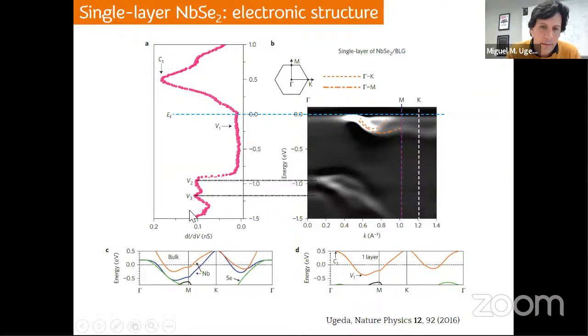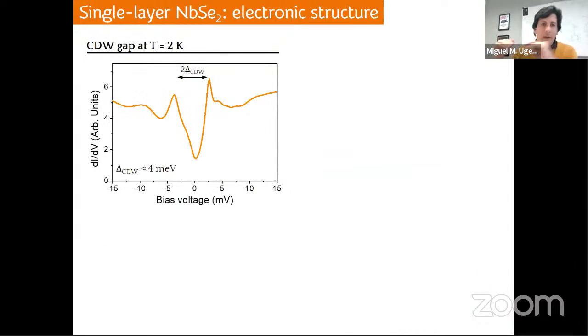And here I show you a dI/dV spectrum taken on this single layer, where you can see the density of states looks like this, and that's it. If you go now close to the Fermi level and at low enough temperatures, for example, I show you a dI/dV curve taken at 2 Kelvin, above the critical temperature for the superconductivity but well below the critical temperature for the charge density wave, what we usually see is a gap with a finite conductivity that we identify as the charge density wave gap, which has a width of 4 milli-electron volt, which fairly corresponds to the critical temperature that we found in this system.